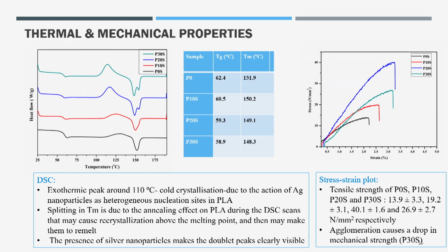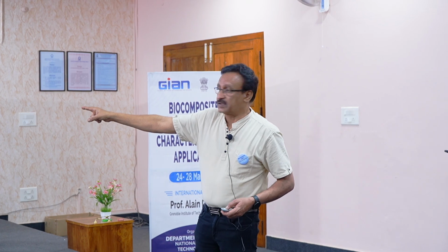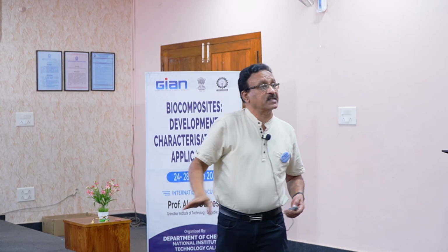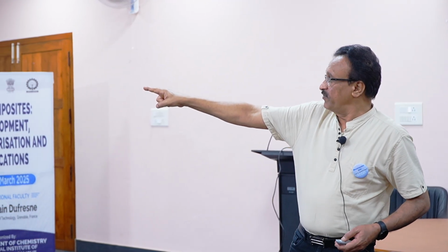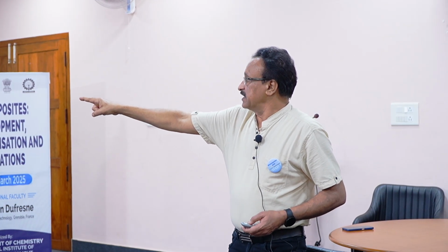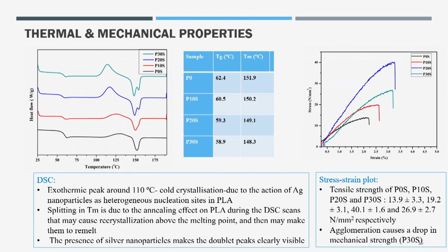For catalytic activity, temperature sensitivity is also important. The TGA curve I did not add, I missed it. But the DSC curve is very useful. From here I can obtain the glass transition, the first dip. This is a DSC. So how do you know it's a DSC curve? Heat flow is always on one axis, and temperature is always on the x-axis. When temperature comes on the x-axis, it is evident that it is a thermal analysis. And you can see that the first dip is the first glass transition, that is the glass transition temperature.